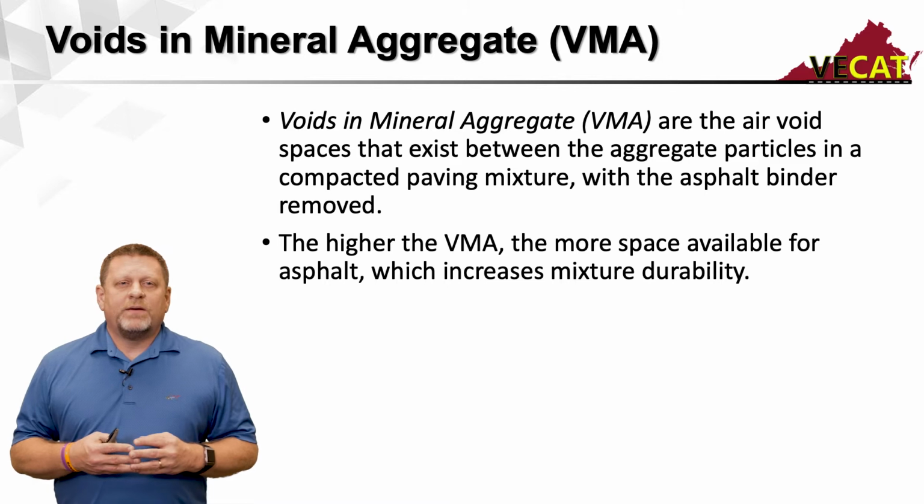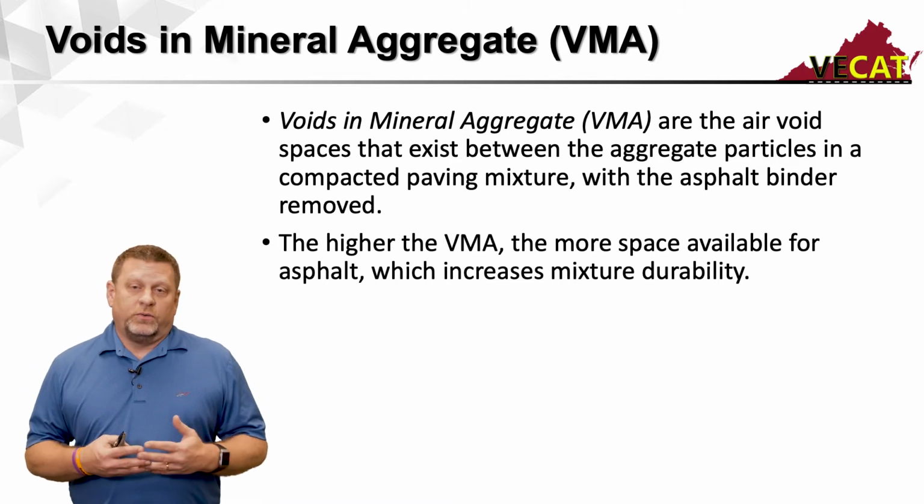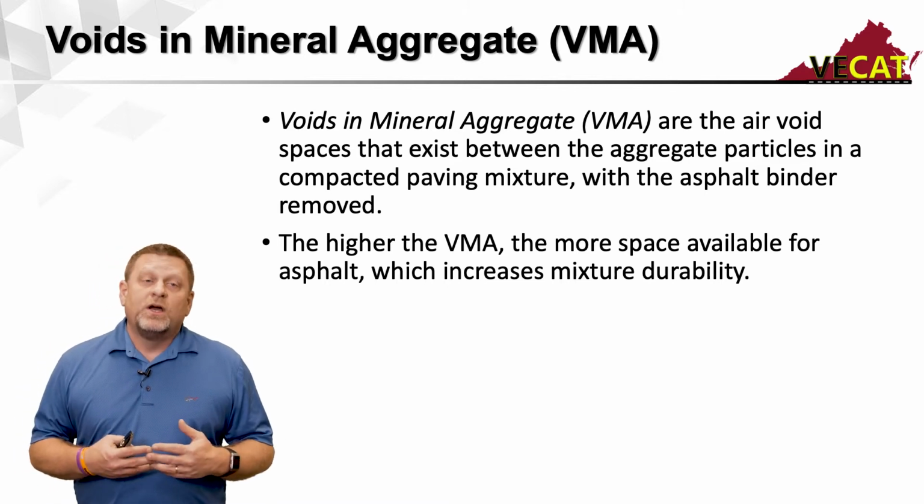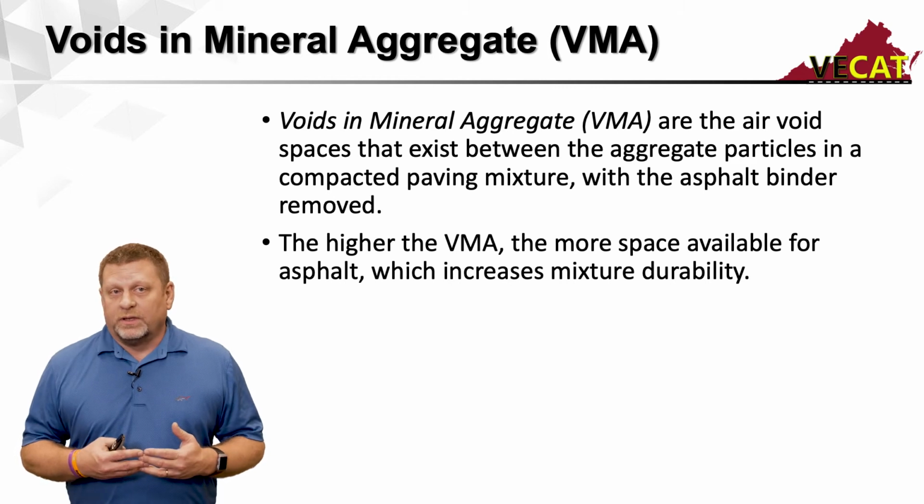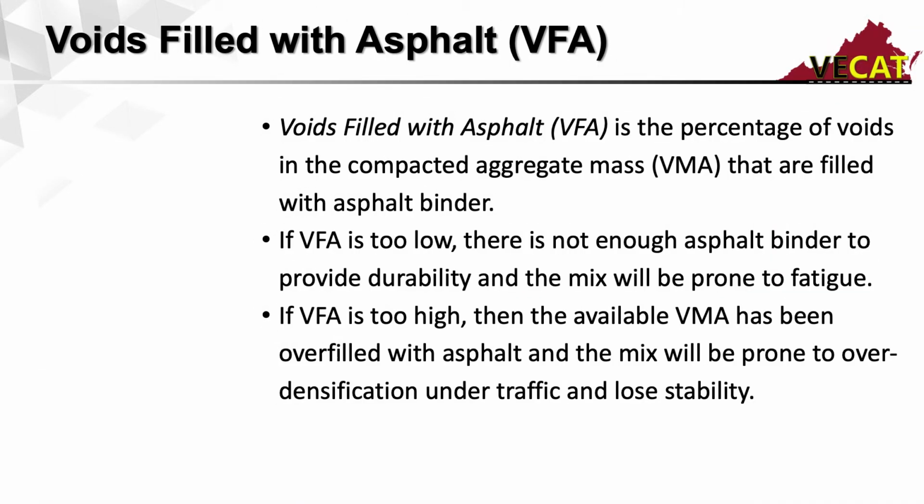So the higher VMA, the more space available to increase the asphalt content, which will basically increase the durability of our mixture. VFA, voids filled with asphalt, is the percentage of voids in the compacted aggregate mass, or basically in our VMA, that are filled with asphalt binder.